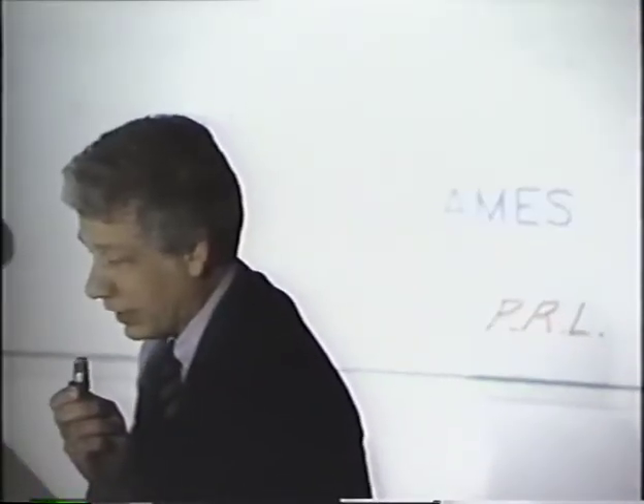In the yttrium barium copper oxide, we were actually working with the 123 compound, thinking that that was the right stuff when we started this. There's obviously a phase with TC of 91 Kelvin. It shows, again, 34% of full Meissner effect, and flux pinning at low fields. I would like to spend a little time concentrating on the magnetization curves and how irreversible they are. The 40-degree superconductor is very reversible, and you can get free energy curves from that.